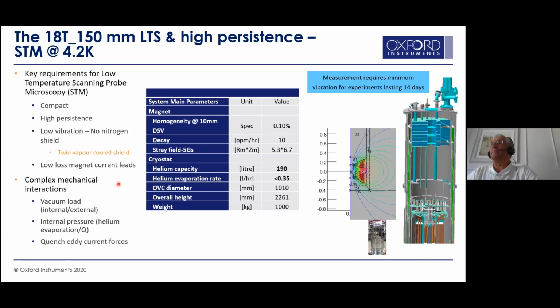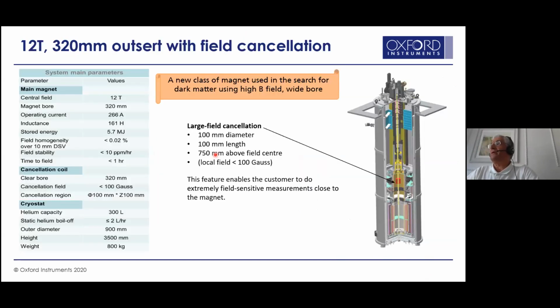Here I'm showing another example of 12 Tesla 320. It has, in addition to the standard magnet system, a cancellation coil. Dark matter applications will require a zero field region. And to do that, we have adapted the cancellation coil, and the total field cancellation extends over a 100 millimeter bore, over 100 millimeter length, with 750 millimeter above the central field. This system has turned out to be very efficient, running 300 liters of helium with 2 liters per hour, and the total weight is less than 800 kilograms.